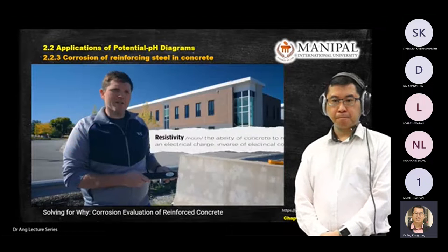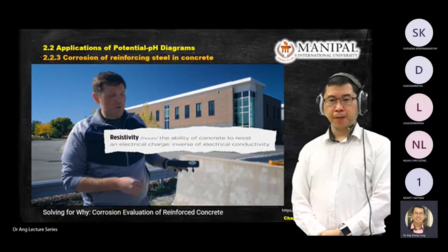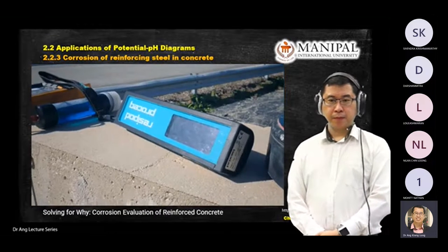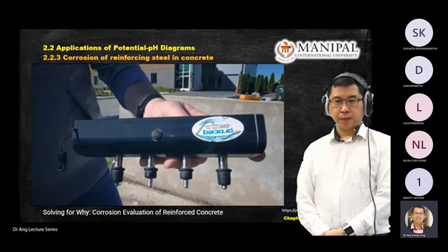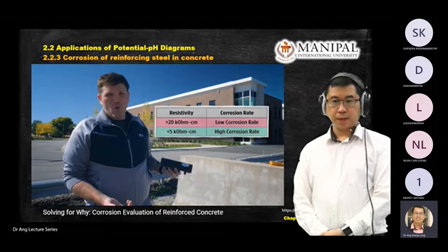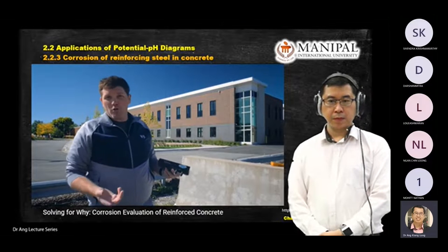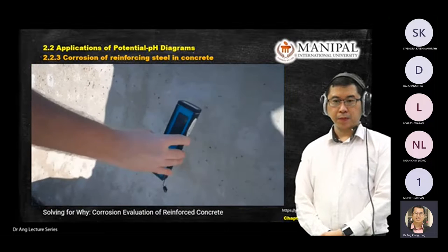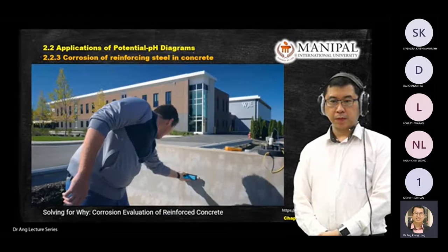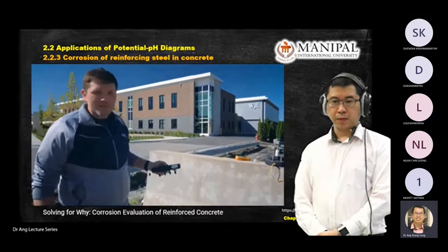The second method we're going to discuss is surface resistivity testing. We have a handheld probe that induces an electrical current in the concrete, and then across these inner electrodes, we measure the voltage change. That gives us a resistivity, which is inversely proportional to the concrete's ability to conduct charge, thus promote corrosion reactions. So to do this test, we place the probe on the concrete surface, take a couple different readings at different orientations, and then record those measurements for later analysis.